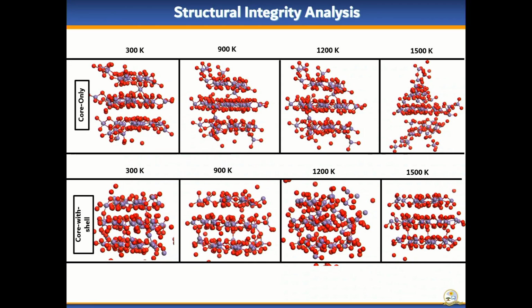We see there's a gradual change, starting from 300 already, with manganese migrating into the lithium layer and forming a tetrahedral coordination. This goes on, and we start seeing some dissociation in our systems. At 1.5, we see that the structure becomes more disordered. But this one is similar to the one above, where we have the shell, which does the interdiffusion between the core and the shell for the atoms. Then we are able to retain our structure.